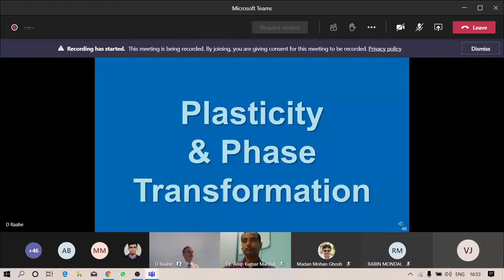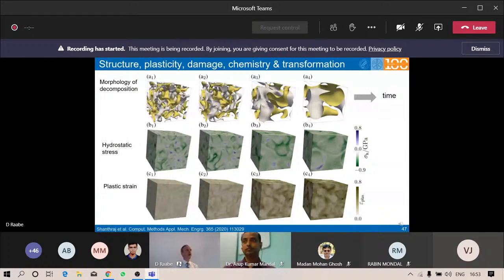We couple this also completely with thermodynamics and with CALPHAD coupling, so that you in the software can also run phase field simulations, but with full appreciation of elasticity and plasticity, such as shown here for the time scale, which goes from left to right, where you see the plastic strain that evolves around the interfaces of this classical Ostwald type phenomenon. So this is just, again, without going much deeper, showing you that we also go on working on combining the crystal plasticity with, of course, anisotropic elasticity and with phase field and phase transformation problems and with fracture problems, because these things are often in modern materials, of course, closely entangled.